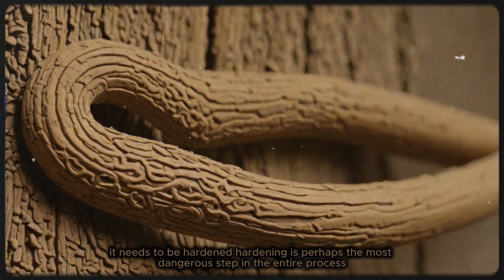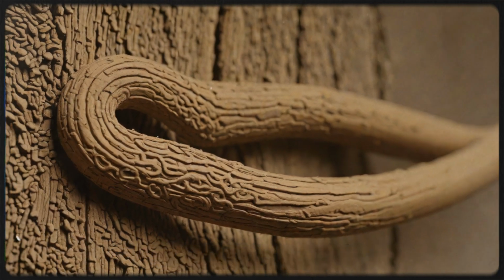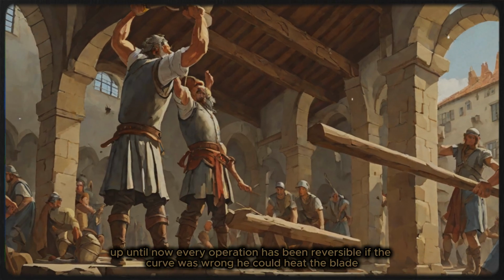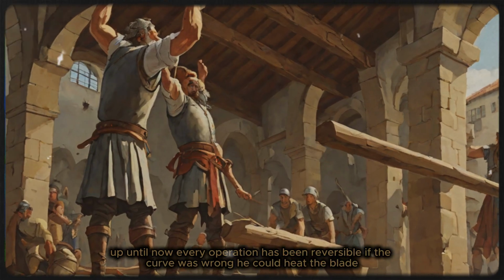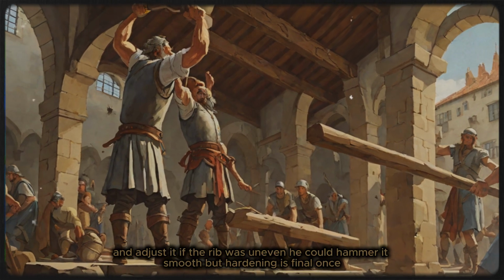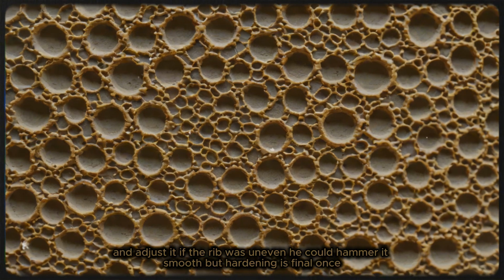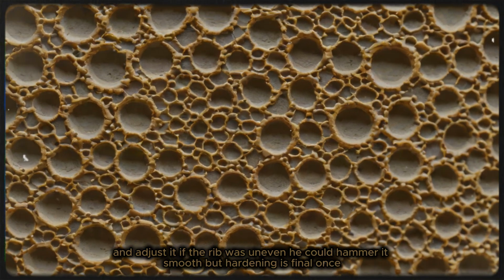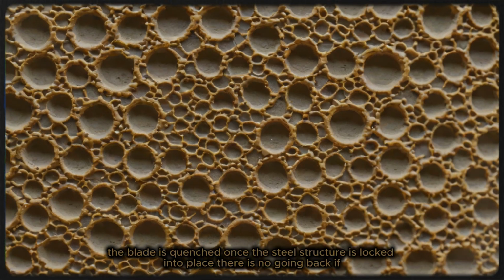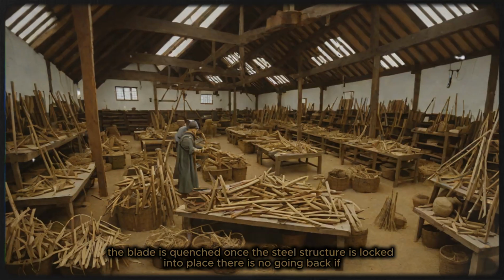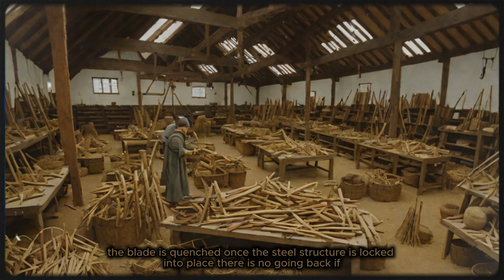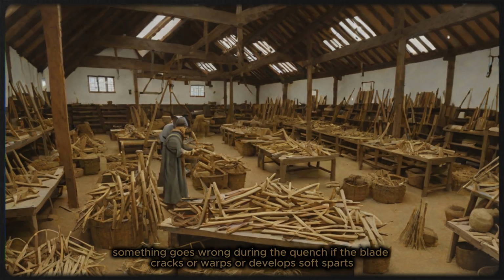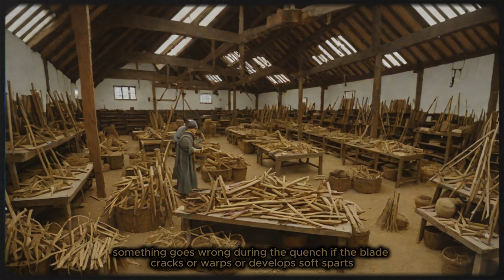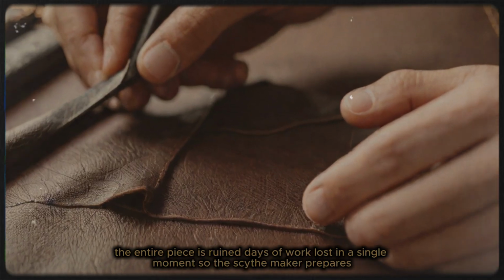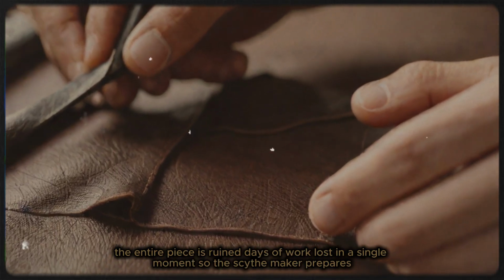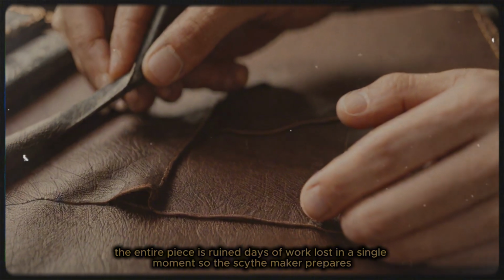Hardening is perhaps the most dangerous step in the entire process. Up until now, every operation has been reversible. If the curve was wrong, he could heat the blade and adjust it. If the rib was uneven, he could hammer it smooth. But hardening is final. Once the blade is quenched, once the steel structure is locked into place, there is no going back. If something goes wrong during the quench, if the blade cracks or warps or develops soft spots, the entire piece is ruined. Days of work lost in a single moment.